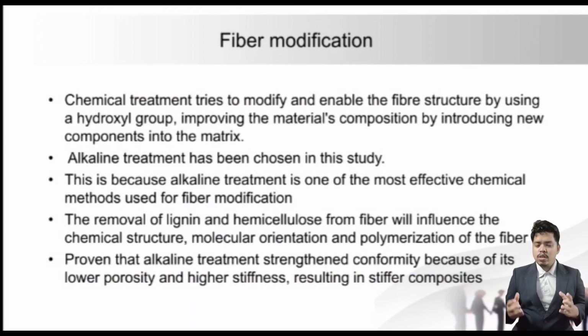Okay, so now I will share with you about the fiber modification. The chemical treatment tries to modify the fiber structure by using a hydroxyl group and improving the material composition by introducing new components into the matrix. Okay, so the alkaline treatment has been chosen in this study. This is because alkaline treatment is one of the most effective chemical methods used for fiber modification. And the removal of lignin and hemicellulose from fiber will influence the chemical structure, molecular orientation and polymerization of the fiber. Okay, and it is proven that alkaline treatment strengthens conformity because of its lower porosity and higher stiffness, resulting in stiffer composites.